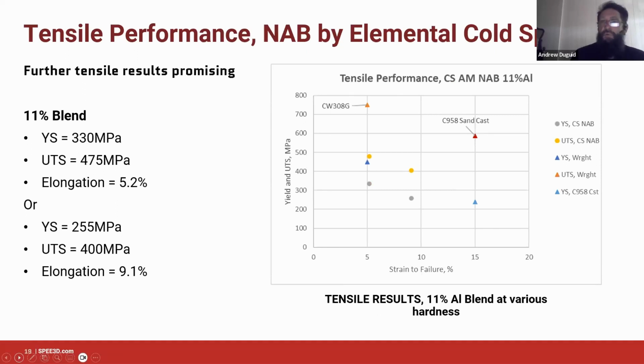So this is with a little bit more optimization, looking at that 11% blend. So we've got the previous data point there, and a second data point that we did with a slightly different heat treatment. And I've added in the 958 sand cast specification there. So how do you gloss that? Well, the first thing is that users have maybe got a choice about what they would prefer. You can have an alloy that's moderately strong at 330 MPa. Not an awful lot of ductility, but there might be applications where you'd want to use it that way.